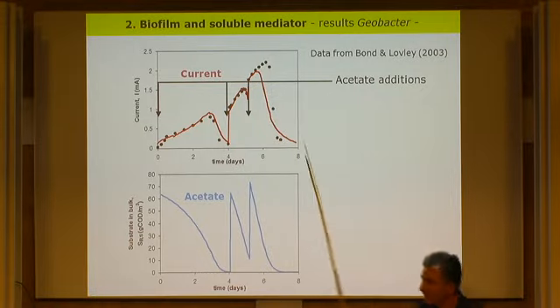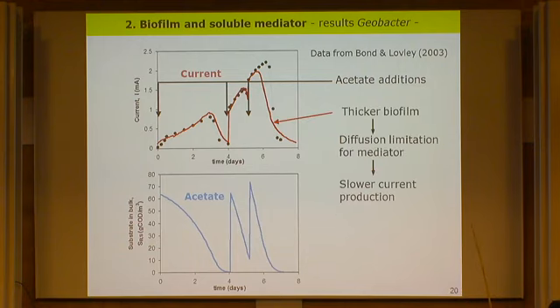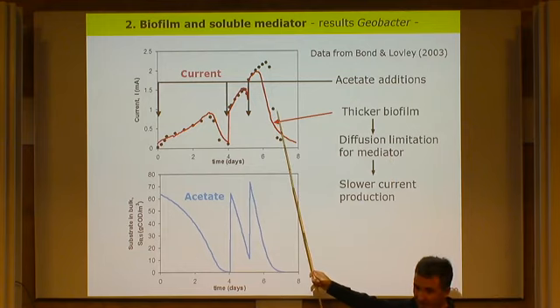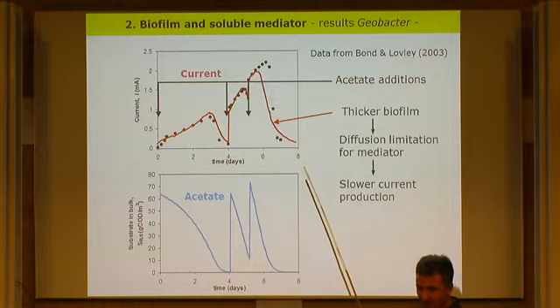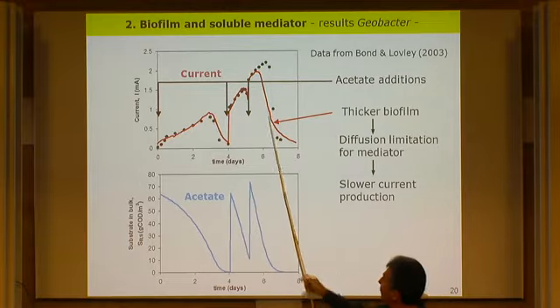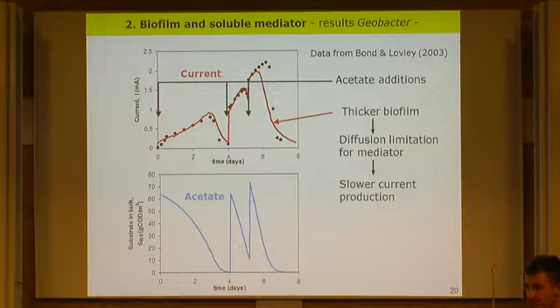It doesn't fit the last part of the experiment. And we think this is because the diffusion in the biofilm is too thick somehow, so that you have too large a diffusional limitation for the mediators. And I think this is quite true, as Jan said, it's difficult to prove something negative. We wanted also to show that Geobacter doesn't work well with these soluble mediators. Geobacter actually can transfer current directly with these wires, a conductive biofilm. So if you have a conductive biofilm, you won't have this diffusion limitation in this case.